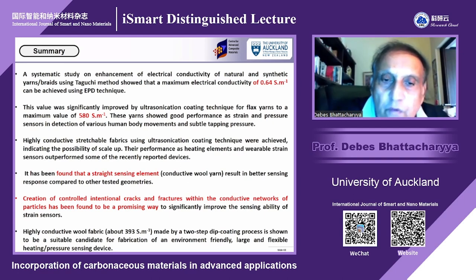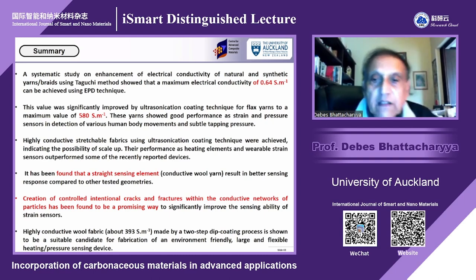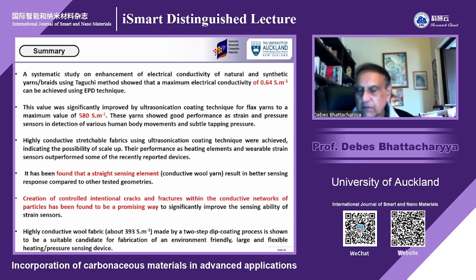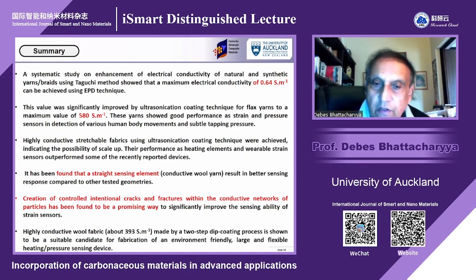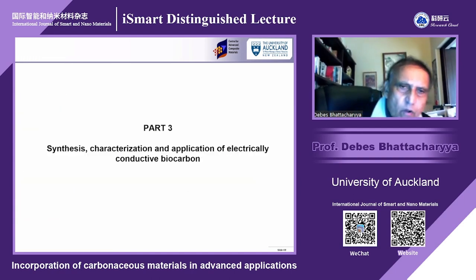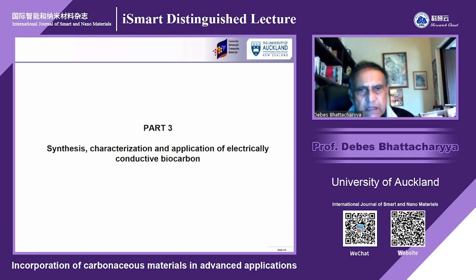And creation of controlled, intentional cracks and fractures within the conductive networks of particles has been found to be a promising way to significantly improve the sensing ability of the strain sensors. It's not very easy to create them. You have to have control, and we need to do much more research to have that kind of control. It is worth doing more research on what sort of control we need, which orientation would produce the best results. With that, I've given you a summary of all these graphene, carbon black, graphene nanoplates.